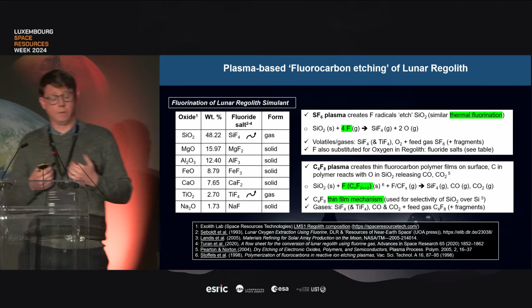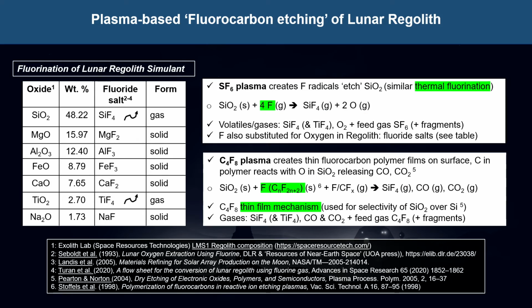For the fluorocarbon chemistry, it's typically a polymer-promoting chemistry, so I can actually see some evidence of thin film formation inside the reactor. This is exploited, maybe not so well understood, but it's definitely exploited to get very high selectivity of silicon dioxide over silicon in the industry. What's happening is the thin film is being created and destroyed continuously, and the carbon inside the thin film is reacting with the oxygen inside the silicon dioxide. So it's not very complete in terms of the understanding of that, but it's certainly being exploited.